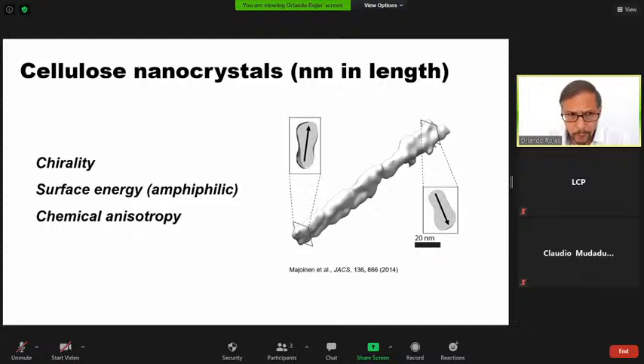The other important cellulose component that is very typical in our research is the case of cellulose nanocrystals. And in Canada especially, cellulose nanocrystals have become of extremely high interest. And there are several units around that are starting to have demo scale production of this nanomaterial. And the main difference, as you can appreciate, is that we have shorter length, rod-like materials, not as fibrillar as the one that I introduced earlier. The other component is that this element is chiral. At the nanoscale, it is a chiral particle, and it's also amphiphilic and has some chemical anisotropy.